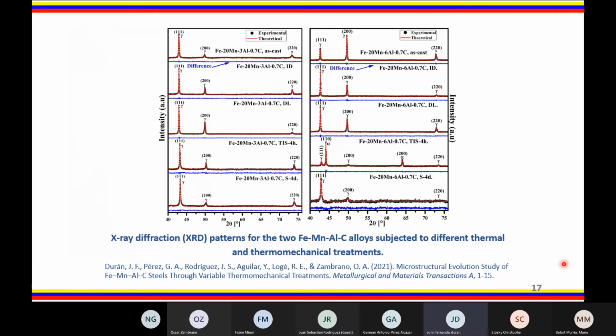All Mössbauer spectroscopy results were validated by X-ray diffraction. In this case, the Rietveld refinements were carried out using 3 austenite phases with small variations of the lattice parameters.